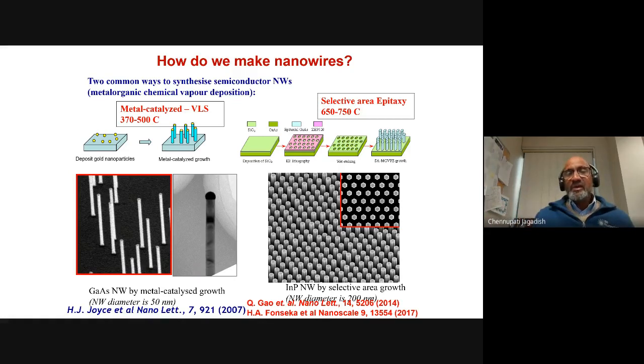So in the case of the selective epitaxy, we don't use any metals, and we deposit some silicon dioxide using plasma-enhanced chemical vapor deposition, and then put some photoresist, for example, do electron beam lithography, create patterns of holes, for example. You transfer these patterns through SiO2, and then you expose the indium phosphide in these holes here. Put this one in the MOCVD reactor, heat up somewhere between 650 to 750 degrees Celsius, and introduce the gases needed for the growth of indium phosphide, in this case trimethyl indium and phosphine. These gases dissociate, and then the nanowire starts growing, for example, here.